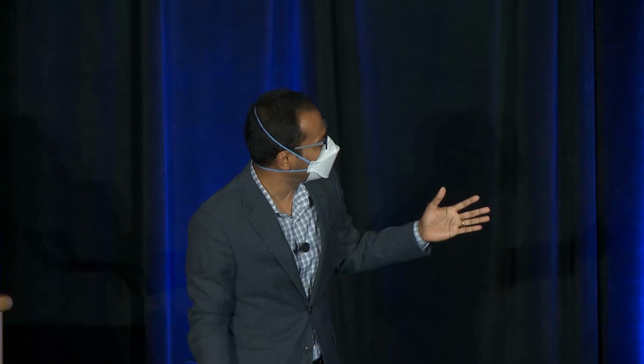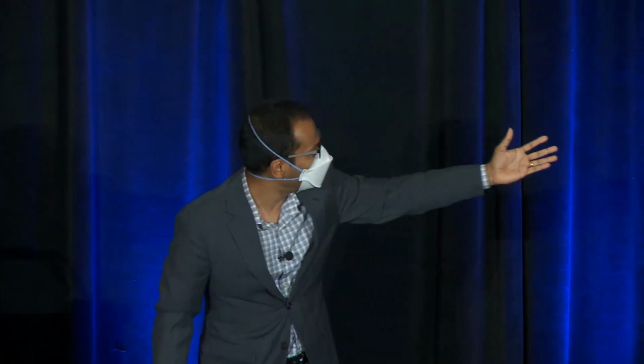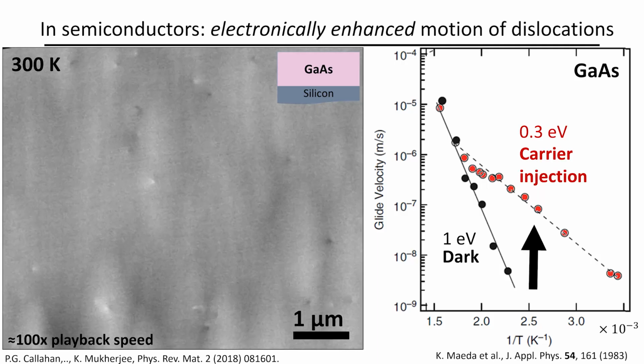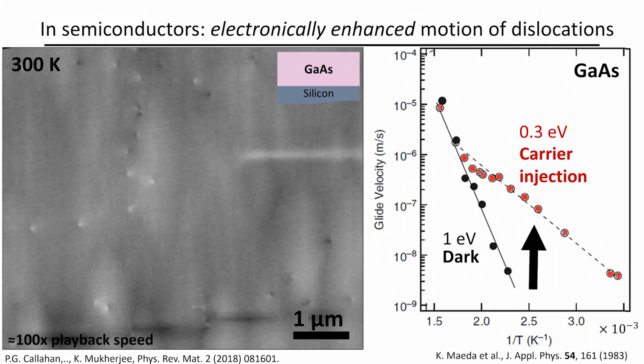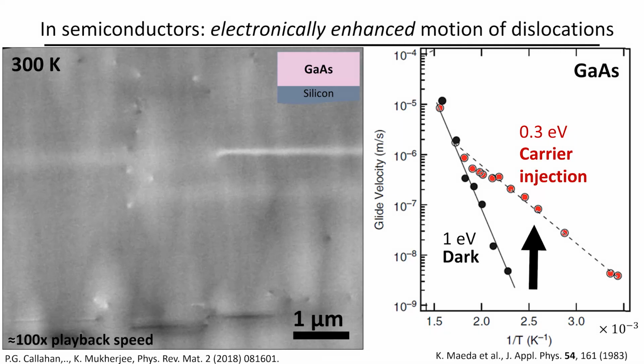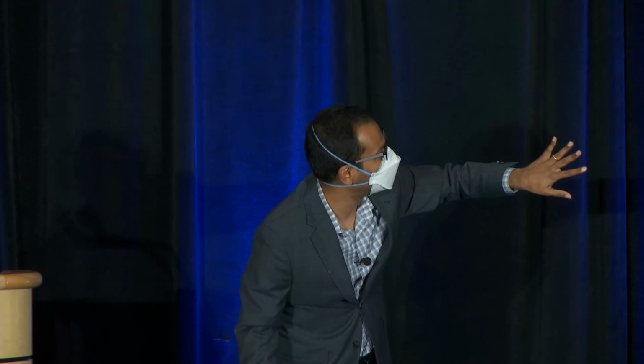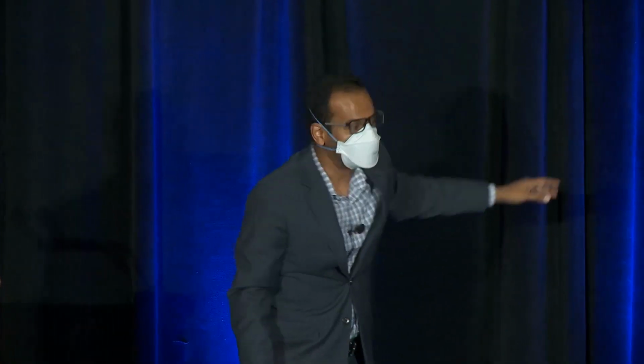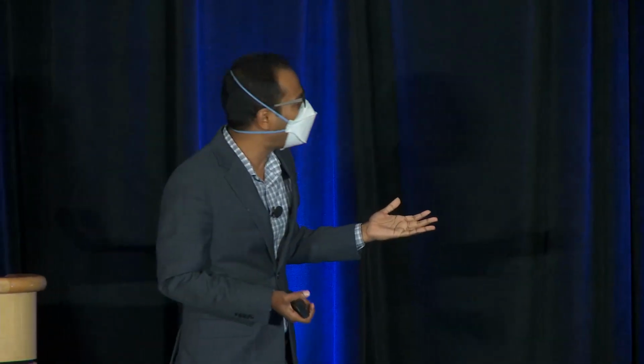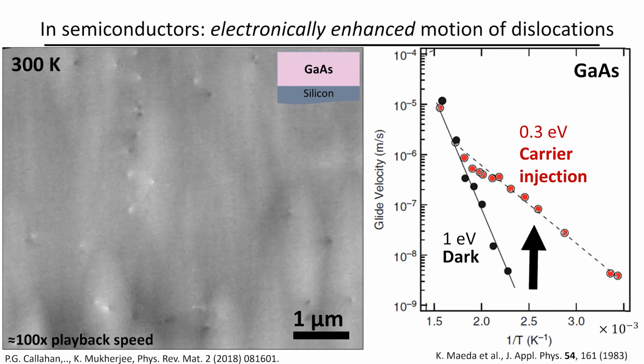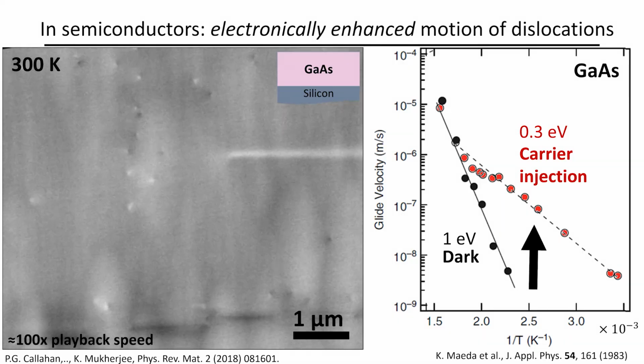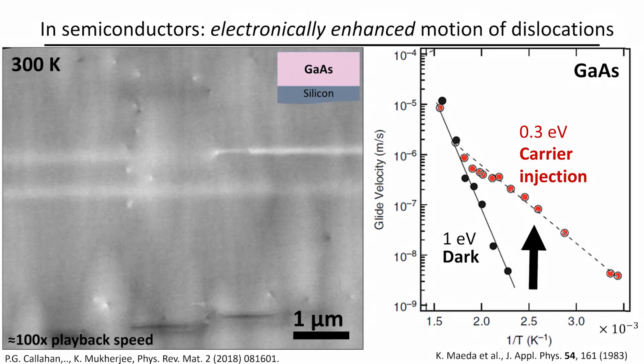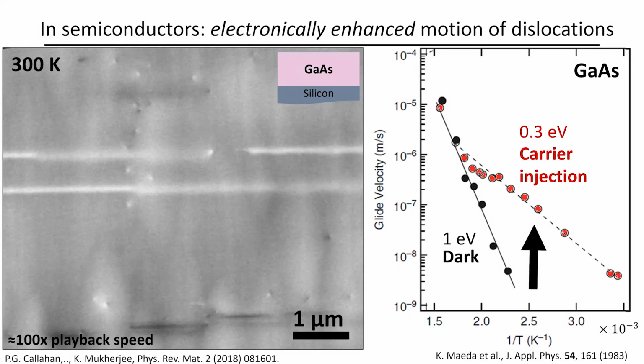So as a material scientist, we've taken these images in the SEM. You're seeing these dislocations move. Actually, you're seeing just the top view. So you're actually seeing the tips of those threading dislocations move. The entire dislocation's actually running into the page. So you see this, and you're very happy. You're like, wow, we can actually see dislocations move. But then when you try and talk to an electrical engineer, you're like, oh, no, this is why the lasers are dying, because the dislocations are moving in our samples when we don't want them to move.